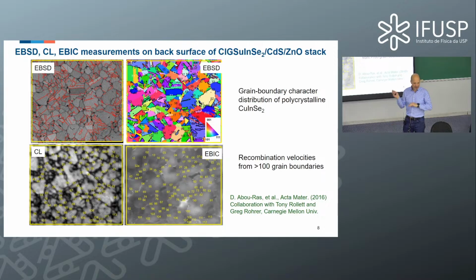I did that manually, yes, and then basically I looked at these various grain boundaries and I identified them in the other results, and basically was able to extract profiles across each and every one of these grain boundaries to have some statistics, yes, so good statistics, more than 100 grain boundaries, and was able to determine the recombination velocity. This is something that we will concentrate on in this presentation. We need some way to quantify the recombination at grain boundaries, and this is done via the recombination velocity.